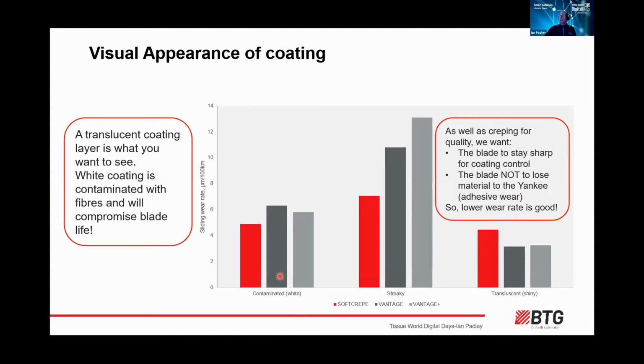White coating, on the other hand, contaminated with blade-eating fines and fibers, that's what we don't want to see. And very often that kind of coating will be quite noisy. The streaky coating is discontinuous on the Yankee, and that's where we start to get higher wear and the possibility of adhesive wear from, if you're using a steel blade, metal to metal contact, which we don't want. Of course, a high-performance ceramic blade doesn't have the adhesive wear issue.